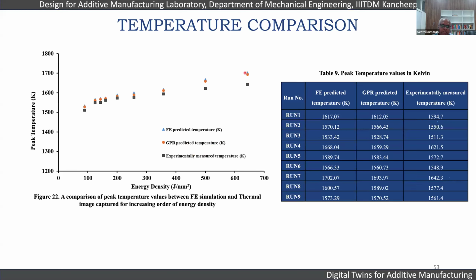But for higher energy density, we have seen some differences in temperature between the experimentally measured and the GPR predicted. This is largely because higher temperature leads to larger gradients in temperature, which becomes a little difficult to model. We observe that above 400 to 600 energy density, where the power is high or the speed is low, there is a little bit of deviation in how either your GPR model or FEM model can predict the accuracy of the experimental measurements.